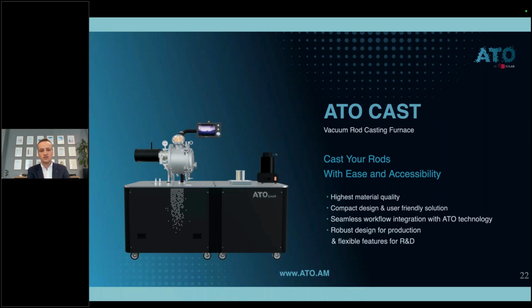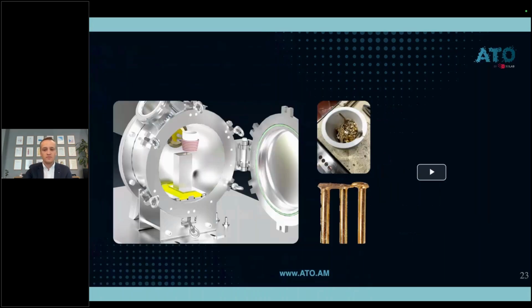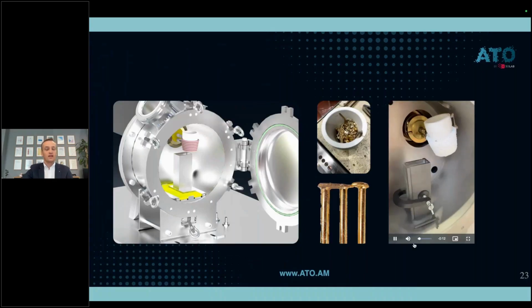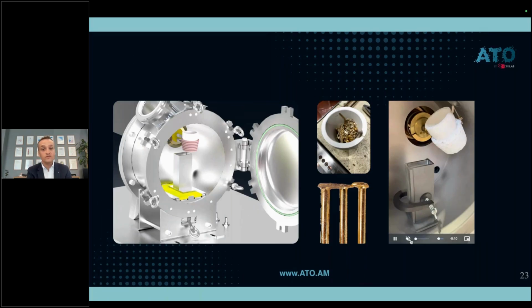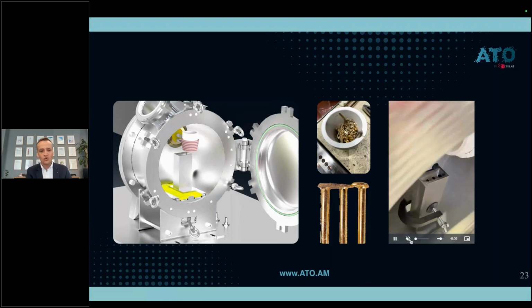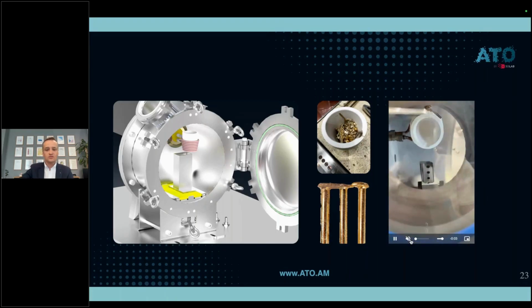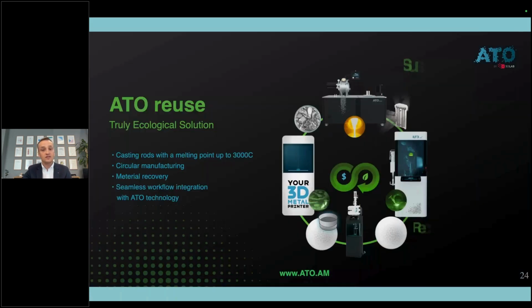Please imagine the situation that you would like to work with scraps. My first thought can be proposing the induction melting system. But for example, you can tell me that you would like to work with materials with a melting point more than the possibility of our induction melting system. In that case, we can use our casting vacuum furnace. We can cast rods, which can be perfectly homogeneous. We can also pre-alloy the material, and with those cast rods, we can go to our main module. Thanks to the ATO Cast, we can achieve this loop.